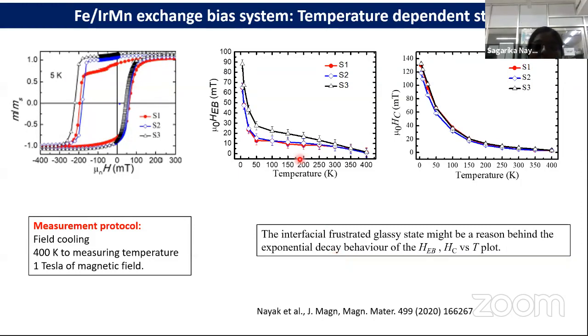In this plot, we can see this is the exchange bias field versus temperature plot, and this is the coercive field versus temperature plot. We can see there is both simultaneous exchange bias field and coercive field. There is a sharp rise in this value below 100 Kelvin, indicating that there is a presence of both rotatable spins and frozen spins at the interface, and they contribute for this large value of coercive field and exchange bias field simultaneously. So from this spin glass model analysis, we can say the interface is frustrated.